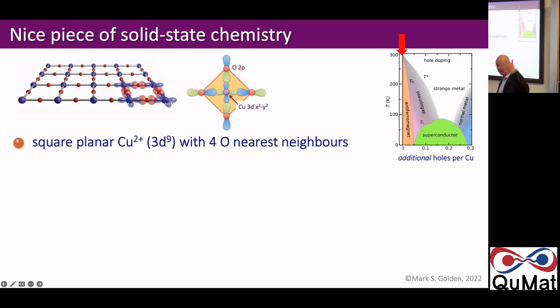That's the highest orbital in the crystal field split structure. And there is one electron in there, and you have these four oxygen 2p orbitals pointing towards the lobes of this copper 3d x squared minus y squared. So for the material without any additional holes per copper, divalent copper 2+, it means it's 3d9. So you have nine electrons and one hole.